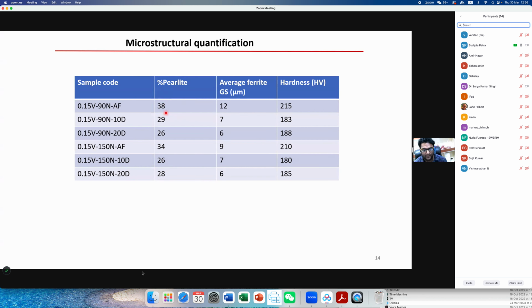The pearlite fraction is a little bit higher in case of the as-forged sample, but when we are cooling at 10 degrees and 20 degrees, it decreased in both the cases. In both the cases, 90N and 150N nitrogen, we are getting higher pearlite in as-forged condition. As we are normalizing it, the pearlite fraction decreases, and obviously the grain size also decreases. At 20 degrees, we are getting at least 6 micrometer grain size.